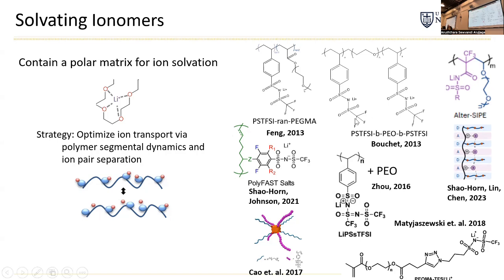So these have the highest conductivity so far. But unfortunately, the conductivity of the lithium in these systems is always limited by the polymer segmental dynamics. So the best we could ever possibly do is what you get when you take lithium salt and you dissolve it in PEO. And we know that that's not good enough for room temperature applications, really. Okay, so they always have to operate at elevated temperature.